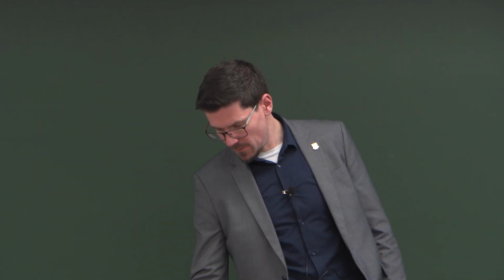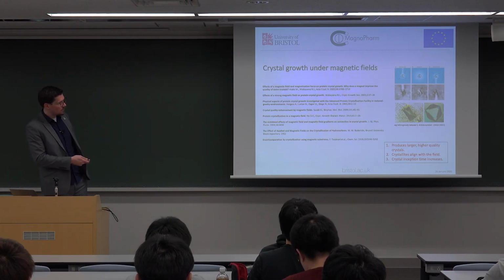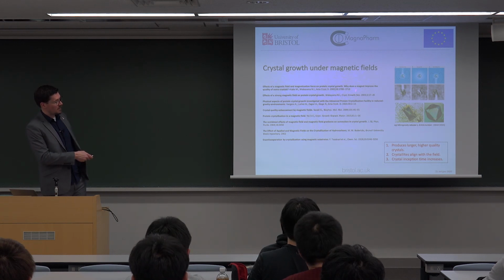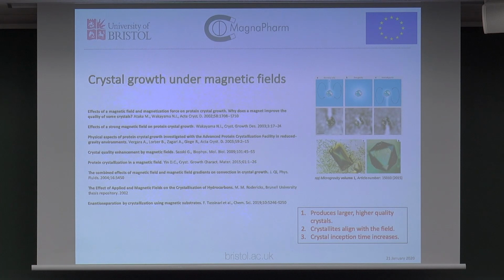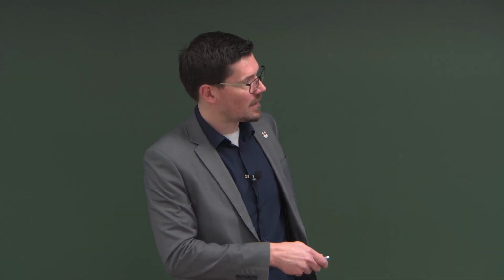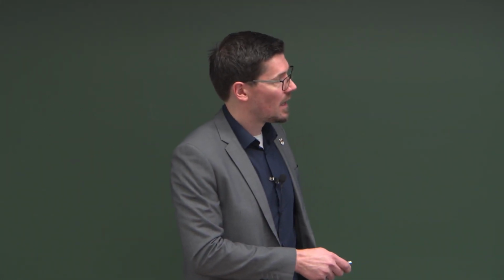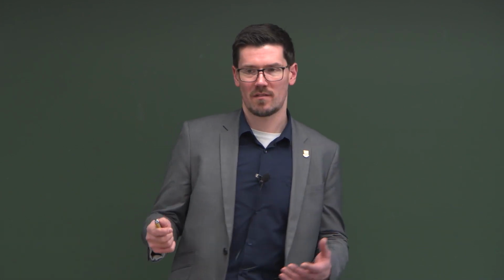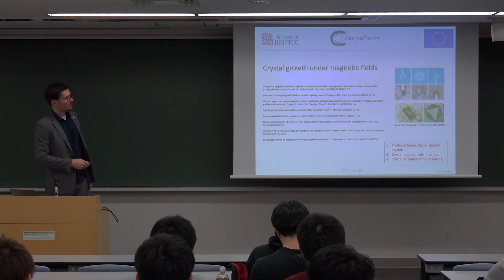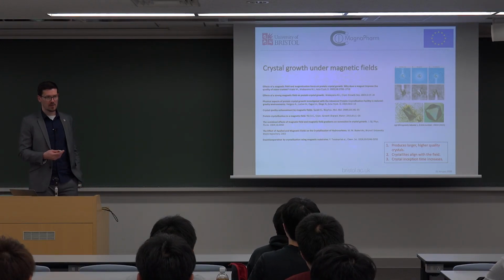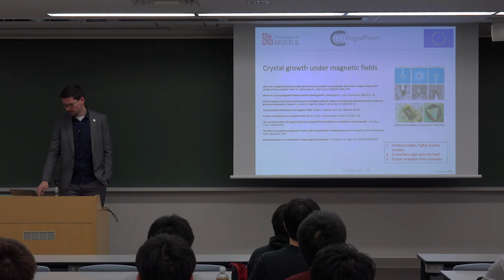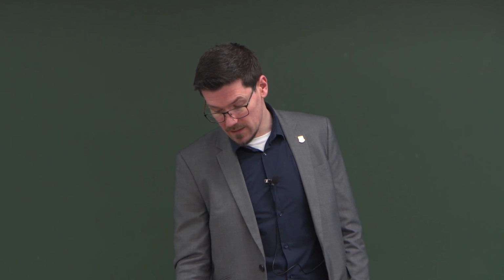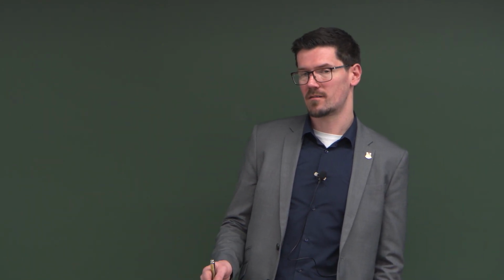Actually, if I go back to this slide, there is some assumption about this experiment up here. I think it was a lysozyme crystal they grew in the presence of a magnetic field. When solute joins a crystal, you get a depletion zone of solvent without the solute in it. And these convection currents of solute-depleted solvent plume up. That causes concentration gradients, and it's thought that those concentration gradients cause nucleation. By using the magnet, you're getting microgravity, you're suppressing this convection, and you're getting better crystals. However, where we were with this, it looked like we were below the threshold for microgravity to have any real effect.